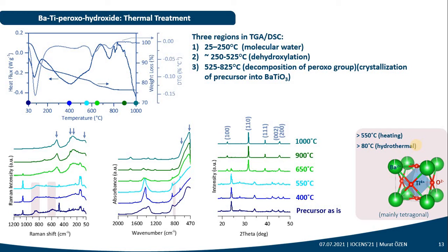Raman, infrared and XRD results support the crystallization at about 550 degrees Celsius. We see that the peroxo band here and here disappear at 550, and the precursor material is transformed into barium titanate above 550 degrees Celsius. XRD results also show the same conclusion. We see that above 550 degrees Celsius, the material is transformed to a single phase barium titanate material, which is actually tetragonal.